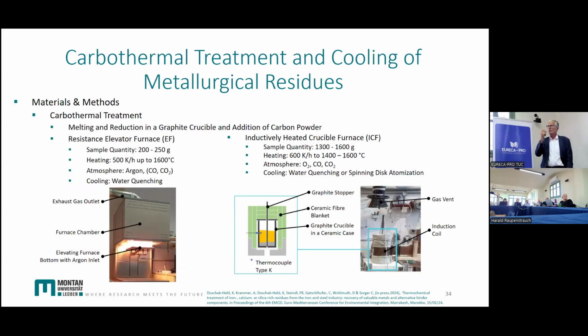So the first step with the mixtures: we make lab scale experiments in this resistance heated furnace for small quantities. We melt it for the carbothermal treatment. The next step is with larger amounts of samples in this inductively heated crucible furnace. We will talk about inductively heated furnaces later in more detail. Here we have larger quantities. We treat them with the reduction experiments, and after that we cool them.